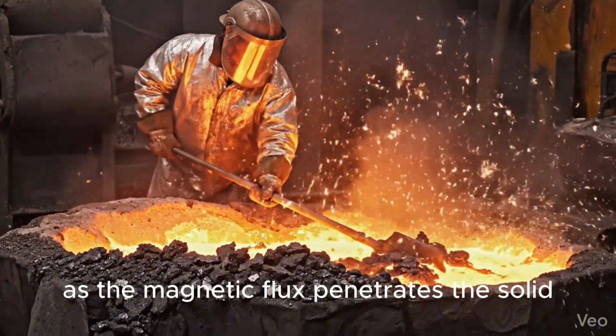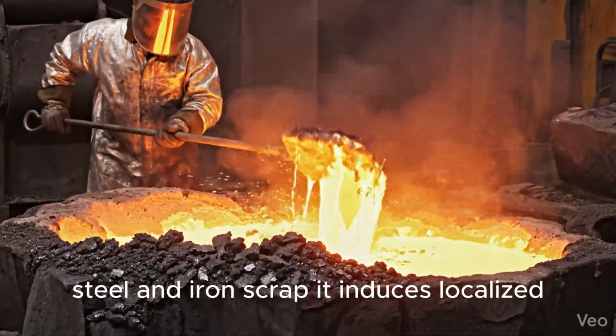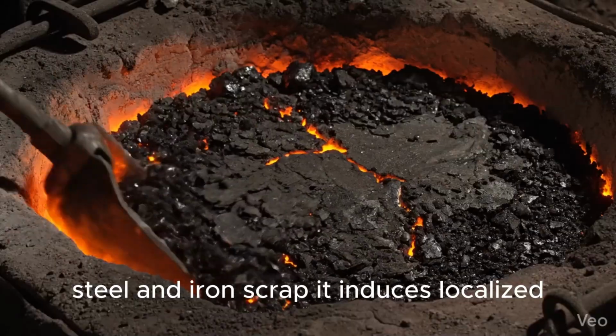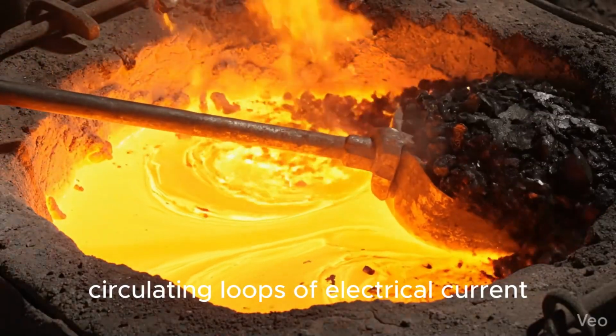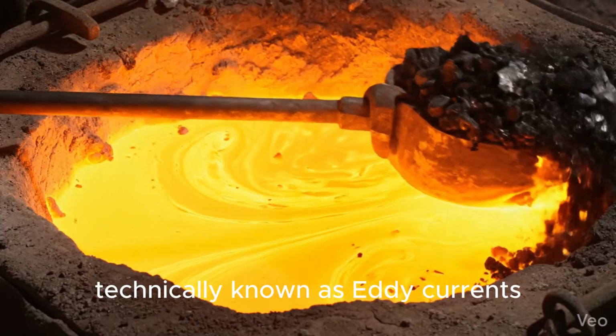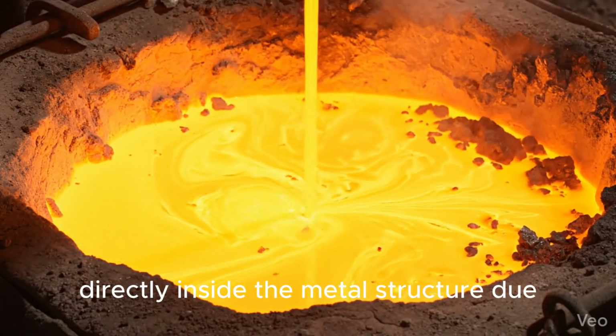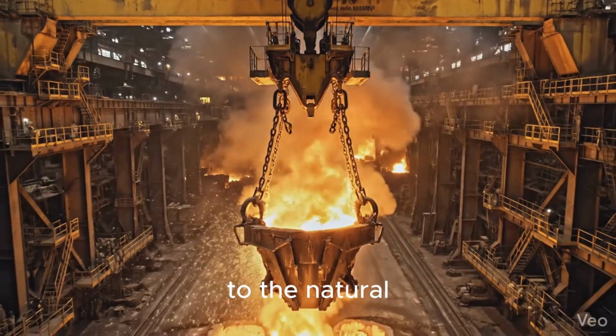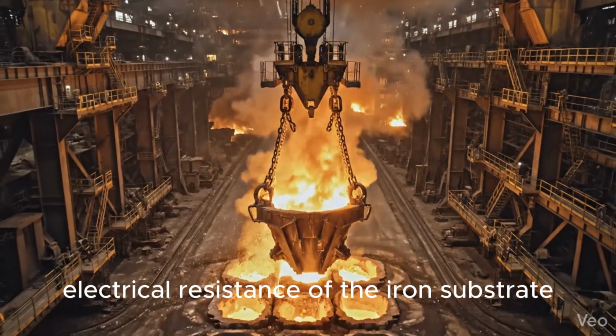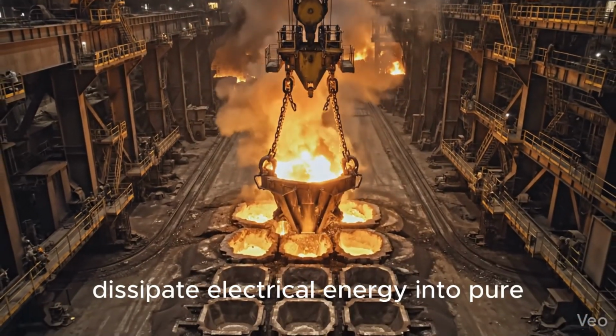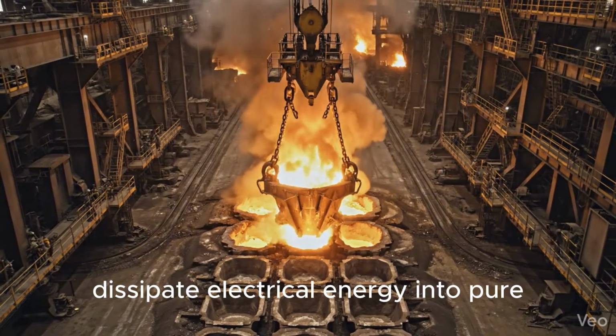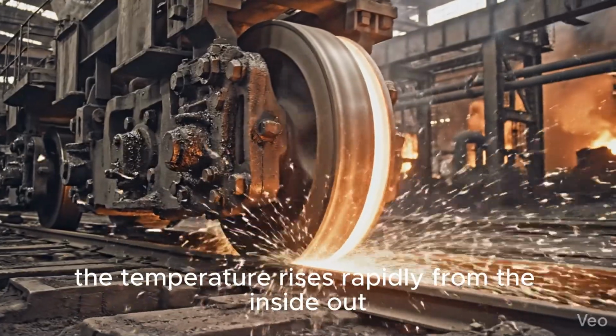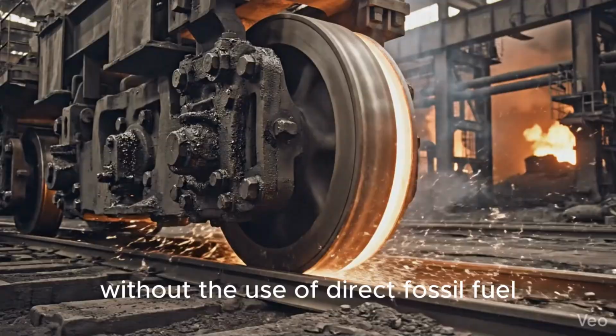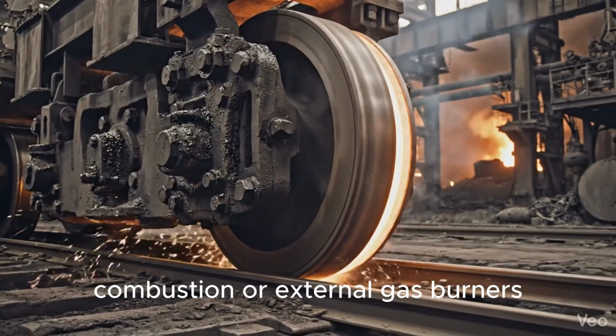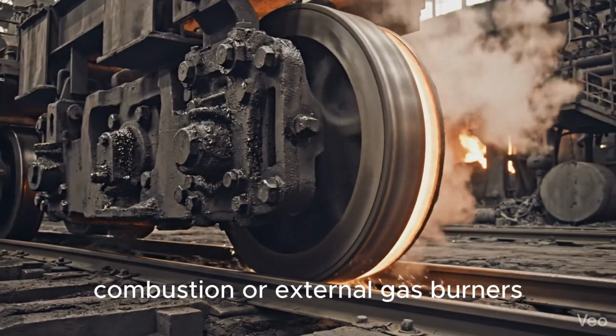As the magnetic flux penetrates the solid steel and iron scrap, it induces localized circulating loops of electrical current, technically known as eddy currents, directly inside the metal structure. Due to the natural electrical resistance of the iron substrate, these eddy currents dissipate electrical energy into pure thermal energy. The temperature rises rapidly from the inside out without the use of direct fossil fuel combustion or external gas burners.